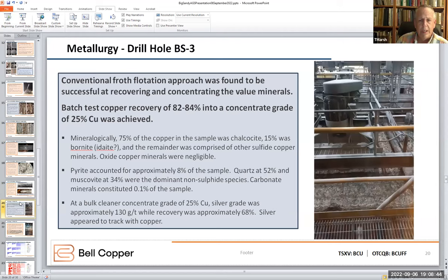Quartz and muscovite are the dominant gangue species. Carbonate minerals are very sparse at about a tenth of a weight percent. And so that opens up the avenue for leaching this stuff with acid without losing acid. Here, the bulk cleaner concentrate on the flotation testing graded 25% copper, 130 grams per ton silver. We lose a bit of the silver in the flotation, but roughly it tracked with the chalcocite.